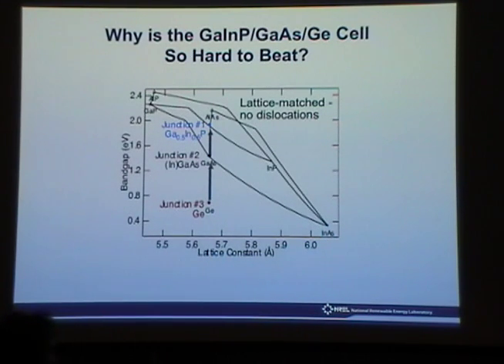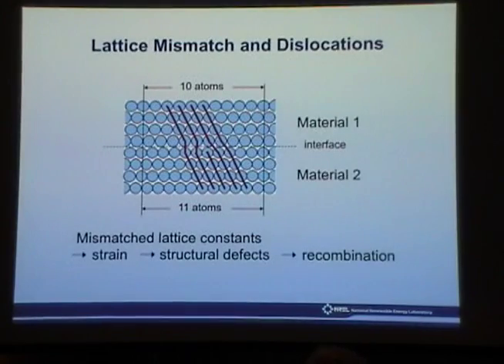These are very, very pure crystalline materials. And if you can grow it lattice matched, then you get essentially no dislocations from one material to the other. Those dislocations can wreck your material. So this cell, despite the fact that it's not current matched, and despite the fact that the germanium is indirect, so you need to have it very, very thick, it's very hard to beat.